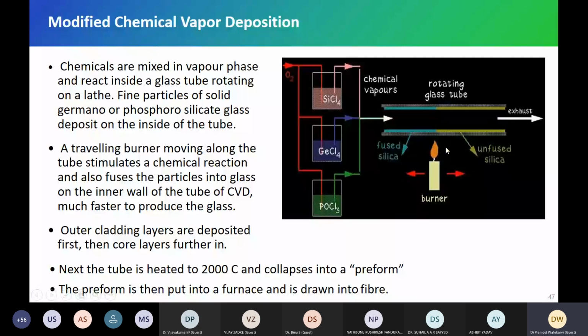We take it, and through this we pass chemical particles: oxygen containing SiCl4 particles, oxygen containing GeCl4 particles, oxygen containing POCl3 particles, or many other liquids you want to send there. For example, if you are sending SiCl4 particles with oxygen, because of heat, SiCl4 plus oxygen gives you SiO2. That powder is deposited here. And when you increase the temperature, that powder densifies to glass. It's very simple.